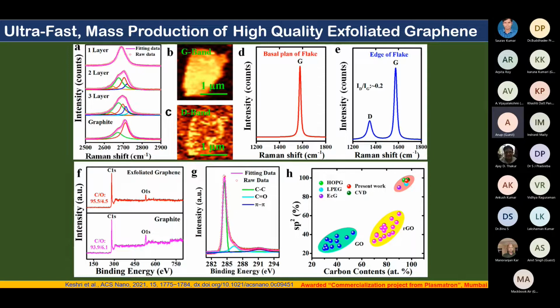The top images you can see here, image A, is the Raman shift versus intensity count, plotted for graphite, 1 layer, 2 layer, 3 layer. Now in the 1 layer, you can see the complete symmetric peak, which you can find around 2700. If this is a complete symmetric peak without any kind of splitting, it is a clear example of the single layer.